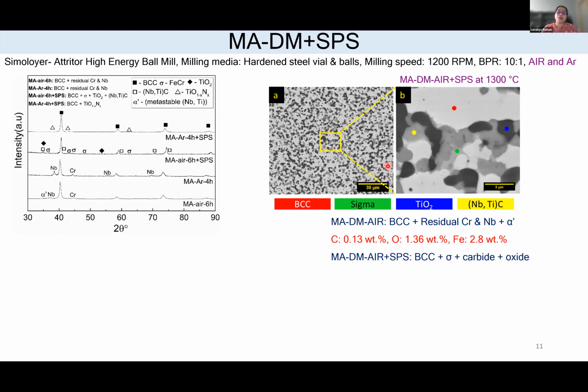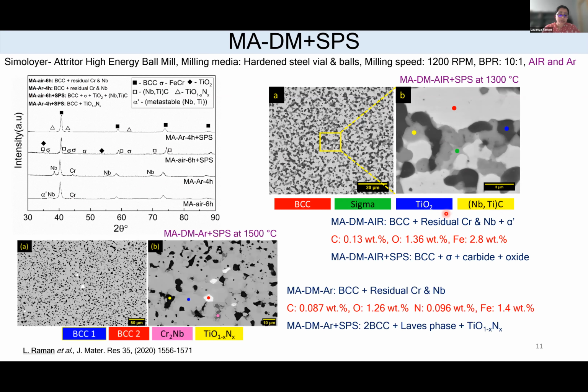Since we carried this out in air atmosphere, as we know, among these elements, titanium has more affinity for oxygen, and it formed TiO2. So basically, we have a BCC major phase with sigma, titanium oxide, and a multi-carbide as the secondary phases. Now, when we carried out the synthesis in argon atmosphere, we have different kinds of phase formation. These residual elements combined together to form a Cr2Nb Laves phase.